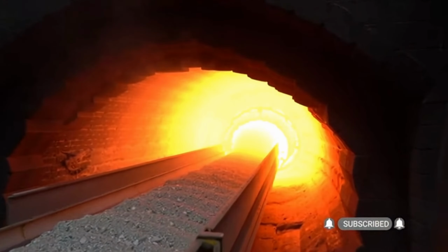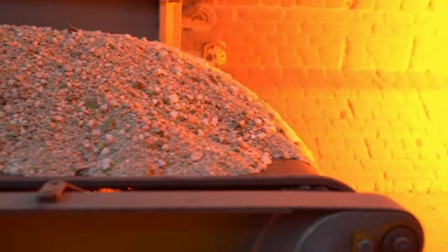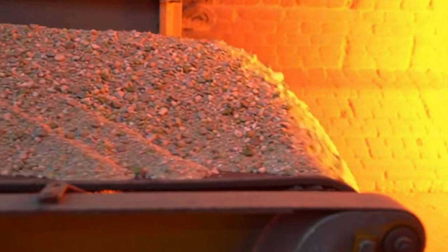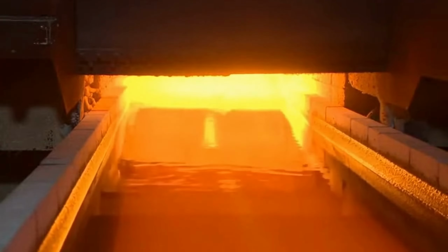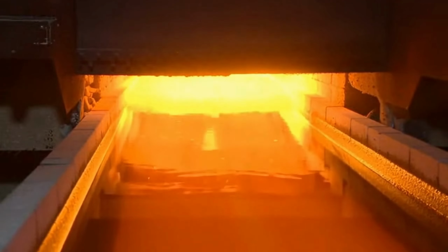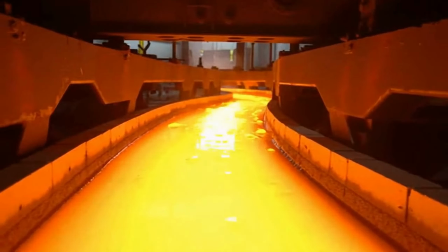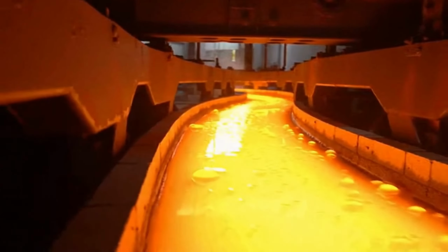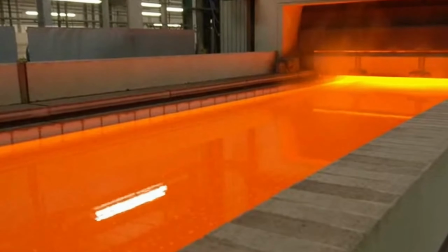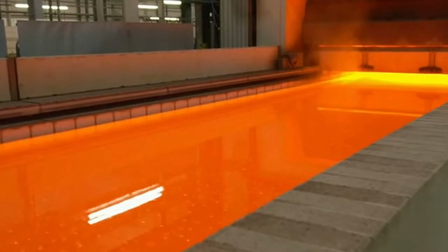Here, at temperatures exceeding 1500 degrees Celsius, these raw materials will undergo a truly incredible transformation, fusing into the liquid glass we know. From raw materials subjected to immense heat, we witness the birth of molten glass. This incredible transformation happens at temperatures exceeding 1500 degrees Celsius, creating a liquid so pure and consistent it flows like a luminous river. This isn't just about melting, it's about perfect consistency.